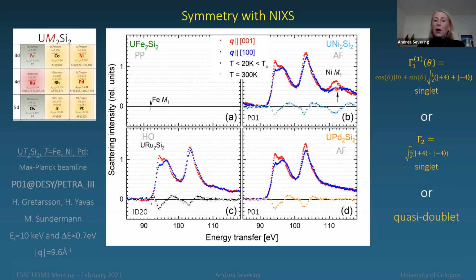And here are now the data of uranium nickel to silicon 2 and uranium palladium to silicon 2, the two antiferromagnets. If you compare this with the ruthenium to silicon 2, and also look at the difference plot, you have to agree that it looks pretty much the same. There's not much happening. We're comparing it with the iron to silicon 2. Also there is not much happening in the energy range of the N4,5 edge. Only in this energy range we see a difference, but this is the nickel M1, a strongly dipole forbidden line, but of course we are in the beyond dipole limit. It's a nice proof actually that we are picking up beyond dipole scattering.